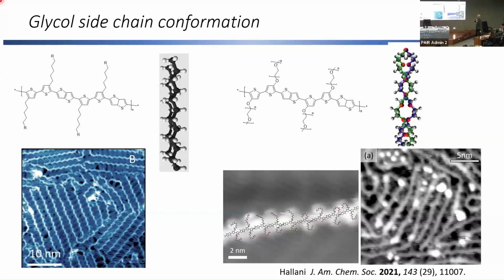So what does that mean? Well, glycol chains are not the same. They pack in a helical way. They're not as ordered, and they don't pack at as high a density. Whereas if you look at PBTTT, this is an alkyl side chain, an all-trans alkyl side chain, very high density, the type of material you might get in a hip replacement, this high-strength polyethylene. Whereas the glycol chains, they wind around each other. And if you look at a single polymer with the glycol chains, you see the side chains here are curling up a little bit. There's not really any room now for interdigitation, just not as ordered.